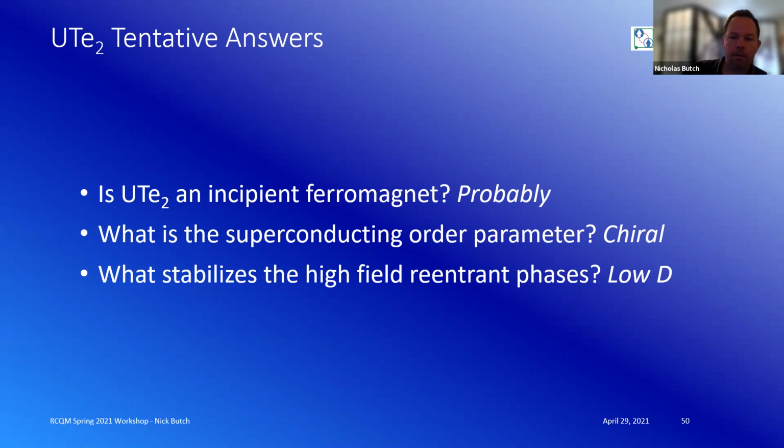We're confident in the rectangular part because the bands that those Fermi surfaces derive from are very high in energy and very dispersive, so they're pretty easy to see. What we're not confident at all about is what's going on near the Fermi level, because that hasn't really been well resolved by photoemission. And for some calculations, that's a hard thing to do at low temperature as well. It doesn't mean that there isn't f weight there, but maybe the statement I should make is, I think the f electrons are integral to the three-dimensionality of the system. There's a question in my mind what exactly that looks like, and also what the temperature dependence should be.